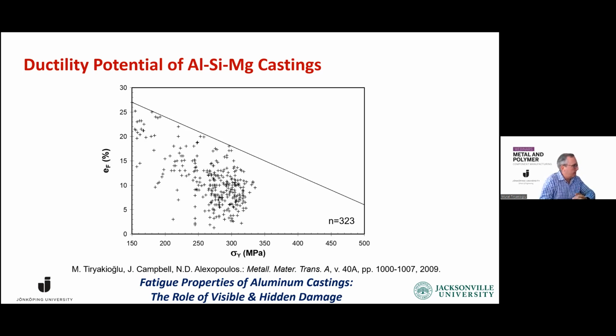So here we have a former study of mine in which I took data from the aerospace and premium casting literature and just put it all on a graph. Here we have yield strength, which is minimally affected by the presence of defects. And here we have elongation on the y-axis, which is strongly affected by the presence of defects. When we look at it, you'll see that there is a clear trend in the maximum points. And again, these all came from actual castings. These were coupons excised from real castings. These are not lab scale. These are not theoretical. This is not something that was specially made. These come from production castings.